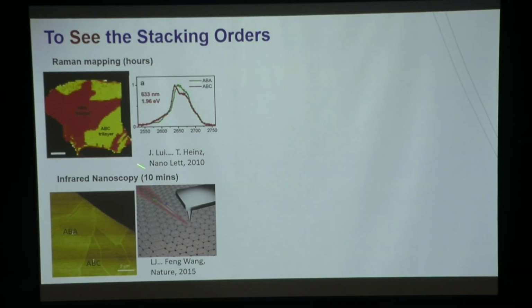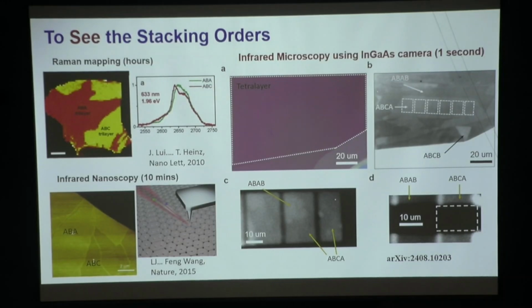What I mean by seeing them is not like spending hours or tens of minutes to scan something point by point. I really want to see something like how your eyes work, right? And it turns out that is possible. It's very simple. The trick is that instead of using visible light, which doesn't really show the different stacking orders within a layer-number homogeneous region, you just increase the photon wavelength that you use to somewhere in the near infrared range. In this case, about 1.7 micrometer, you can already see the difference between ABCA, which is rhombohedral, and ABAB, which is Bernal stacking. You can even see a third stacking order, which is ABCB in the 4 layer. This takes you less than a second, and you can readily differentiate the different stacking orders.